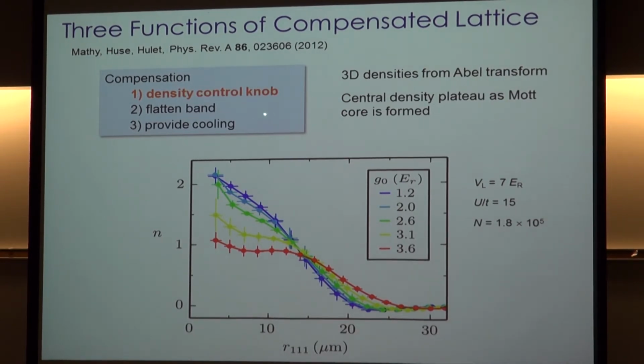So the first thing is to control the density. These are various strengths of the compensation beam. And you can see that by tuning the compensation appropriately, we can get into the Mott phase, whereas without compensation or with low compensation, it forms a band insulator. So that's a density control knob: you just simply change that intensity.